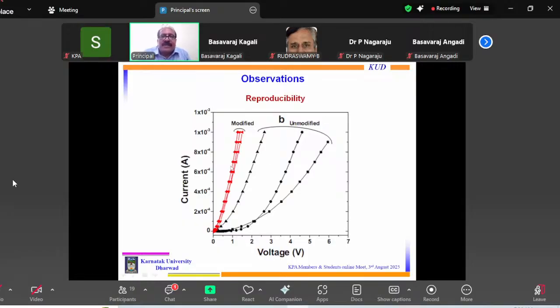But now what we did is we took bare silicon and created devices, which I call unmodified. I don't put any organic molecules. I try to measure different junctions, same semiconductor, same material. I am creating multiple junctions, small dots. When I measure from dot to dot, I can see that for unmodified there is no consistency. There is a large variation in current-voltage. However, if I modify, I can again measure from different junctions, and I can see the repeatability is quite good. The molecular junctions are going to create more stable and homogeneous devices.